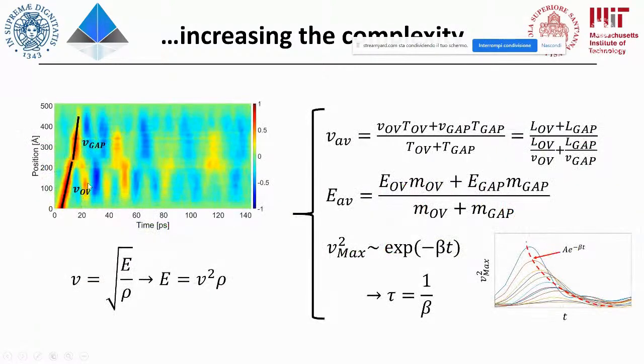And this is also something that is really connected to the macro scale and how bone works, because if we hit our bones with very fast loads, bone structures are able to dissipate energy very fast, avoiding any damage on the structure itself. Then another nice thing to see is the change of slope that is between the overlap and the gap region. And we can see it better here. And therefore, we can understand separately the velocity of the waves in the overlap and in the gap region. And we can model the wave transmission in both regions separately. And this is, up to our knowledge, the first study in which scientists did this.